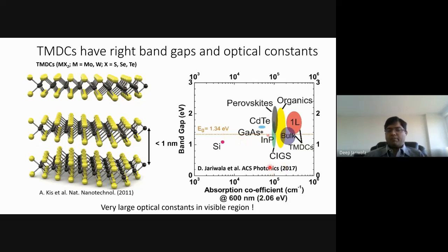And so when we started comparing all the photovoltaic semiconductors with these TMDCs, we found that not only do they have the right optical constants, but they have some of the largest absorption coefficients in the visible part of the spectrum compared to all other photovoltaic semiconductors. They're even more absorbing than perovskites, 10 times more than gallium arsenide, 100 times more than silicon. So they're really very good materials in terms of light absorption, in the visible part of the spectrum, which is where you want them to be.